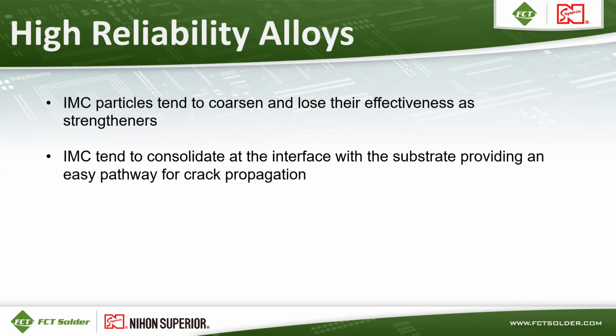Intermetallic compounds also consolidate at the interface of the solder joint and the board pad, and the solder joint and the component lead. Those areas where they're consolidating can become brittle spots. And if enough intermetallic congregates in one area, that can become a crack pathway, and so the solder joint could potentially crack through those areas.